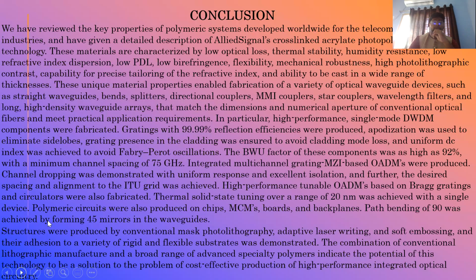Next slide. Conclusion. We have reviewed the key properties of polymeric systems developed worldwide for the telecom and datacom industries and have given a detailed description of Allied Signal cross-linked acrylate photopolymer waveguide technology. These materials are characterized by low optical loss, thermal stability, humidity resistance, low refractive index dispersion, low PDL, low birefringence, flexibility, mechanical robustness, high photolithographic contrast, capability of precise tailoring of the refractive index, and ability to cast a wide range of thicknesses.